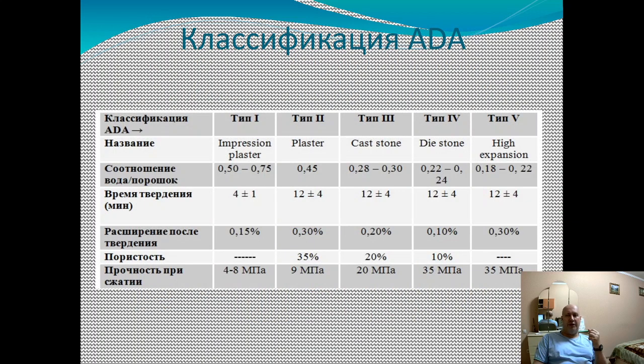Here you can see the classification, the table about these types of gypsum. And if you look at this one, you can see that type 4 and type 5 mostly have the same characteristics. It has one very important difference. The expansion coefficient of type 4 is about 0.1%, and the expansion coefficient of type 5 is about 0.3%. And so this one has a higher expansion coefficient. So it's usually used for big works, including big works on implants. For example, total works.